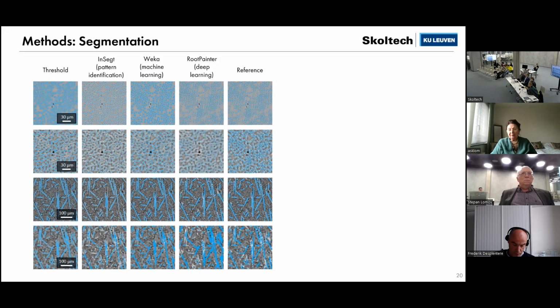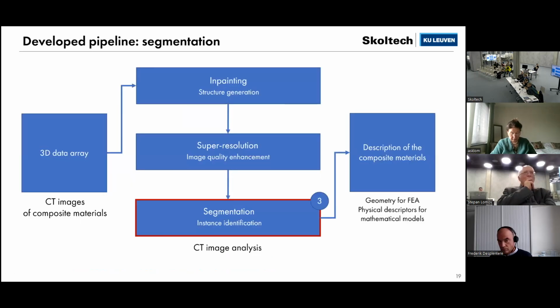We can take this data, for example, find all the trajectories of our fibers, and after that say to the algorithm, make the fibers with these trajectories, with this specific fiber diameter. Yes, it's also possible, and it will be very good with fewer parameters compared to pixel-based. It will also be parametric, but again, without images and without this kind of segmentation, these models wouldn't be possible because there is no such generative algorithm. I'm not talking about models of material. I'm talking about models of the fibers, and it's a very different story.